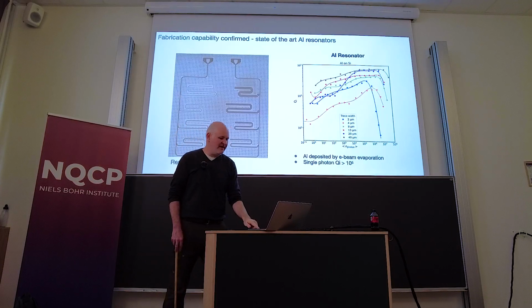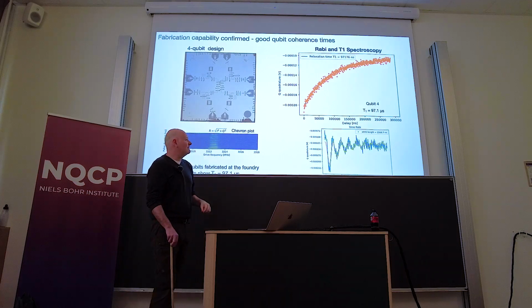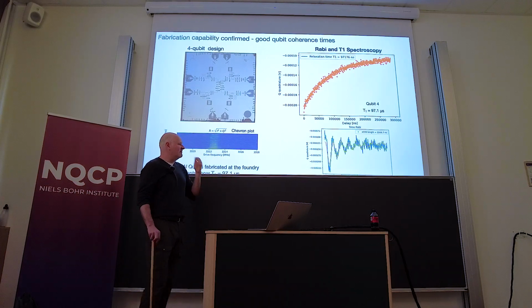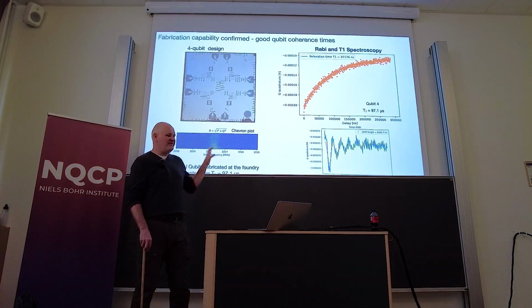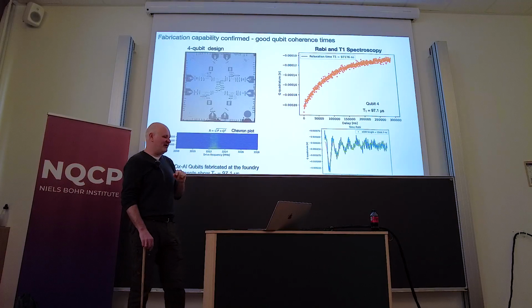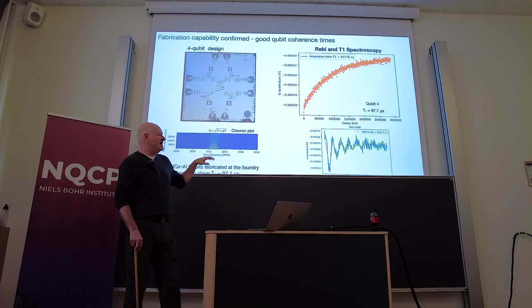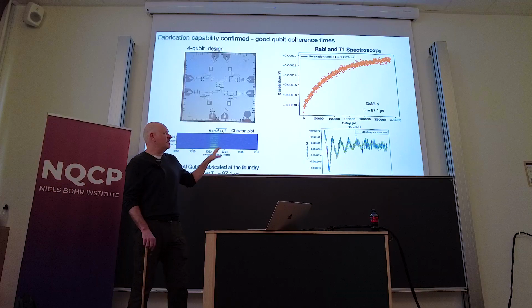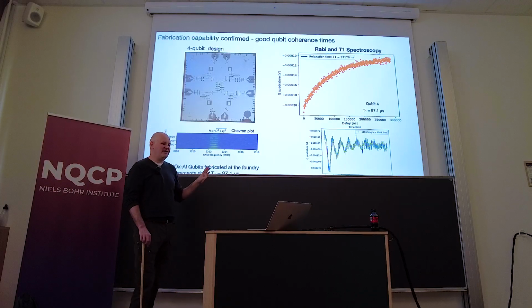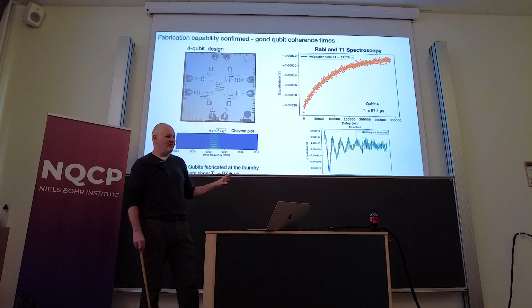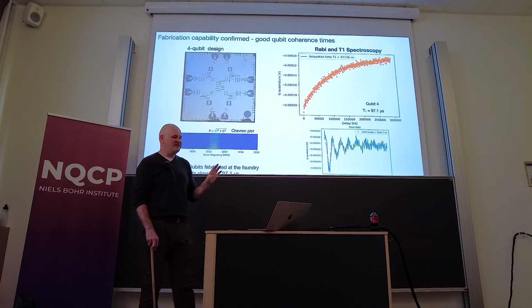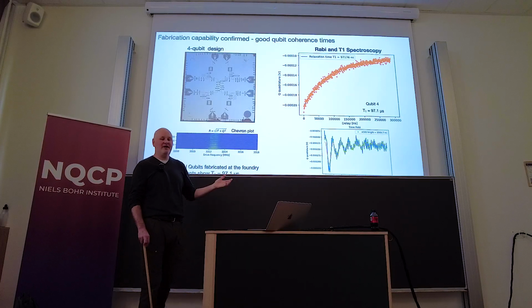Then we look at the full devices, and again, we don't have a huge number of data points on these, for a reason I'll mention in a second, but we were able to get T1 times on the order of 100 microseconds, which again is not record-breaking, but it is solid. And that's really all I wanted, to have solid devices, and this was for 2 reasons. One, again, to confirm that we could do it.